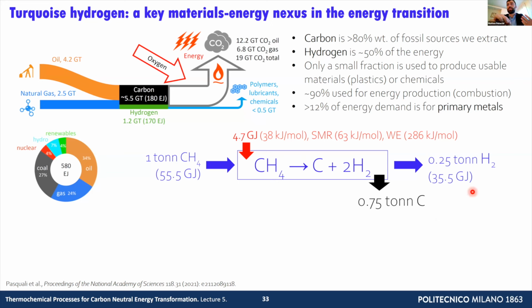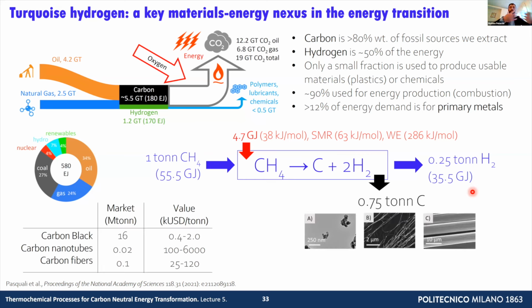You're left with 0.25 ton of hydrogen that still has 35 or so gigajoules of energy. The issue is that, of course, you're producing 0.75 ton of carbon, and you need to find an application for this carbon. There are many applications. Carbon black is one of the most produced chemicals worldwide, about 16 million tons per year, but it's worth only a few thousand USD per ton. But we can foresee producing carbon nanotubes, for example, that have outstanding properties, or carbon fibers for many different applications.